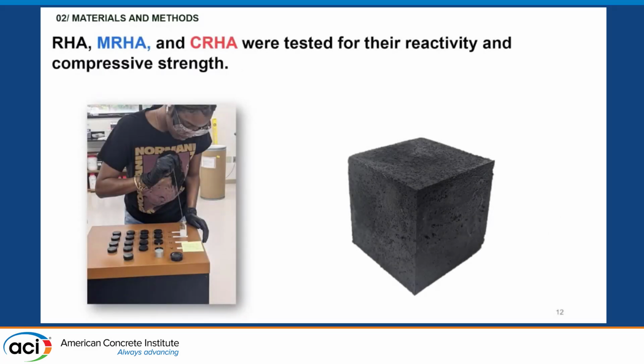And so the RHA, the MRHA, and the CRHA were tested for their reactivity and their compressive strength. And as you can see there on the left, there's one of the amazing undergraduate students who works in our lab doing some isothermal calorimetry for the R3 reactivity test. And then on the right there is kind of what one of the cubes after putting the milled rice hull ash ends up looking like.